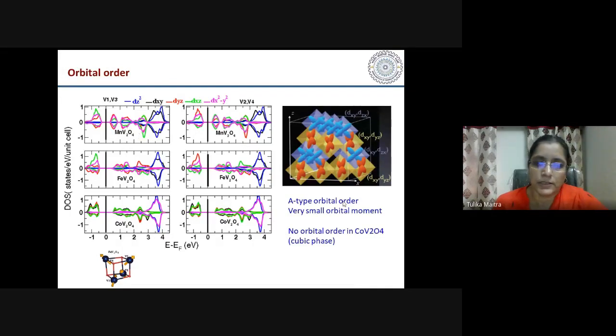this orbital order is A-type orbital ordering, as shown here. That is, in the ab plane we have all the same orbitals, but when we move along the c direction, we go from yz to xz to yz to xz again. Okay, so this is called A-type orbital order. Similar to the A-type magnetic order, one can have A-type orbital order, which we find for FeV2O4 and MnV2O4. Whereas in CoV2O4, there is no structural transition, so there is no orbital order seen in the cubic phase.